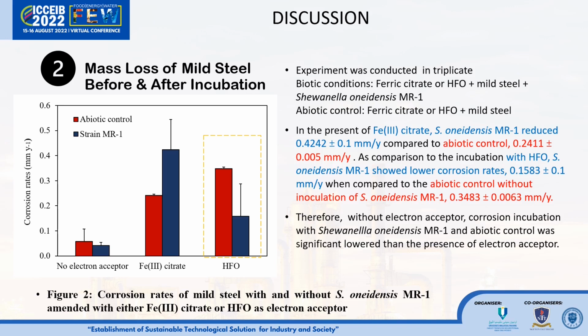In comparison, in the incubation with HFO, Shewanella oneidensis MR-1 showed lower corrosion rates, which is 0.1583 mm per year, when compared to the abiotic control without inoculation of Shewanella oneidensis MR-1, which was 0.3483 mm per year. Therefore, without electron acceptor, corrosion incubation with Shewanella and abiotic control was significantly lower than in the presence of electron acceptor. Yet, for HFO reduction, there was inconsistent data compared to the earlier ferrozine test, because mass loss of mild steel was very noticeably higher in abiotic control compared to the presence of Shewanella.